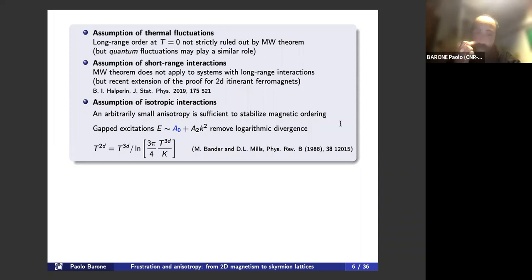But the crucial assumption is the one of isotropic interactions. And it is relatively easy to understand this, because the presence of an arbitrarily small anisotropy basically gaps the excitation spectrum. And the presence of a gap in the excitation spectrum means that one can remove the logarithmic divergence by introducing a low energy cutoff in the integral that I showed before.